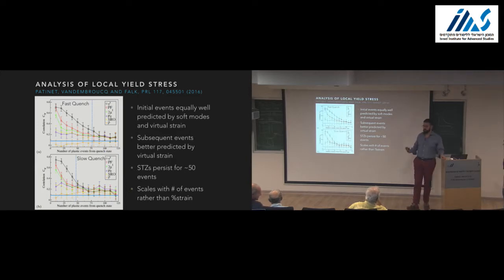So far we've only imposed pure shear. We haven't included dilation and expansion. Although the data's in there, we just haven't pulled it out. You could look to see, as you apply the pure shear, is there a spike in, or a maximum in the pressure in the local region as a function of the strain. And from that, you could get out something like an activation volume associated with the defects. So, that may be interesting. I mean, clearly it's more sensitive to the shear. The activation volume might tell you that putting it under hydrostatic compression inhibits the transformation or vice versa.